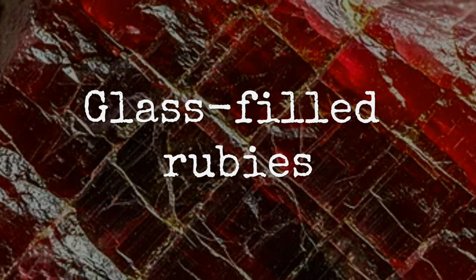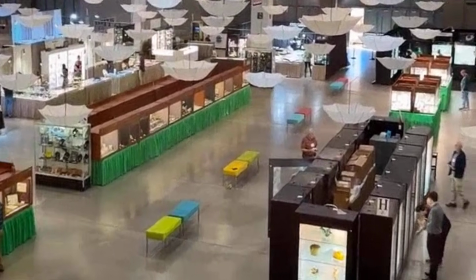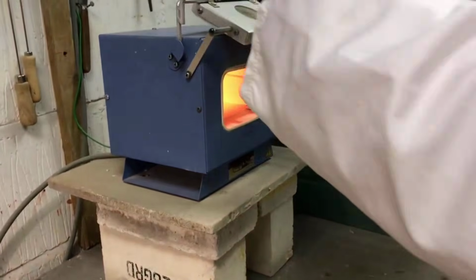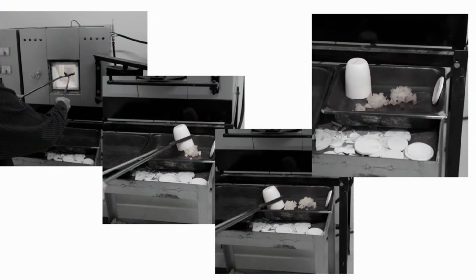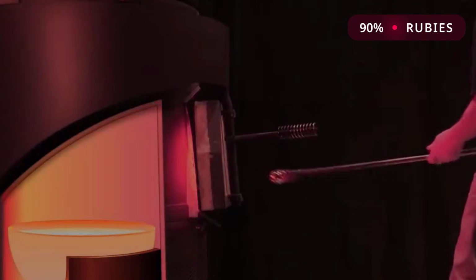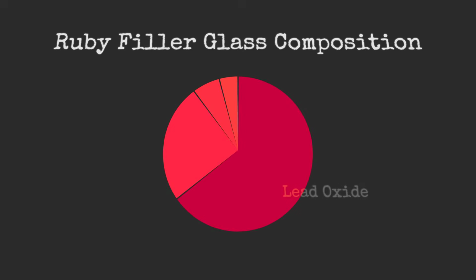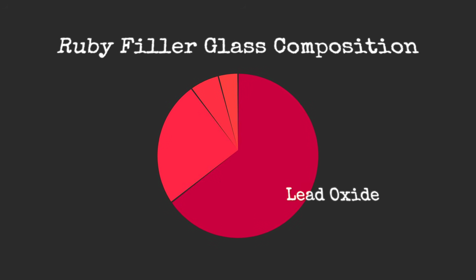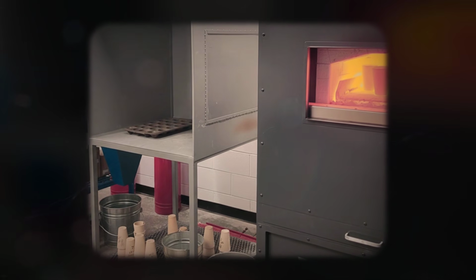Glass-filled rubies. I see these everywhere, from Bangkok's Silom Road tourist traps to the back tables at the Tucson Gem Show. The process is brutal in its simplicity. Low-grade ruby gets cleaned with acid, then heated to between 900 and 1100 degrees Celsius. Molten lead glass, 43 to 76% lead oxide by weight, flows into every surface-reaching fracture. The refractive index of that glass sits between 1.7 and 1.8, close enough to corundum's 1.762 that the fill nearly disappears to the naked eye.